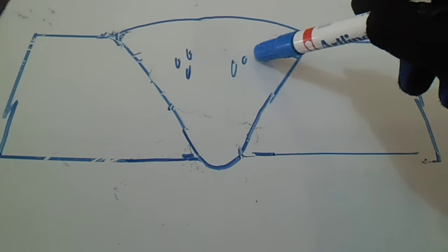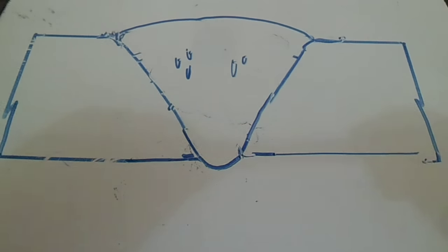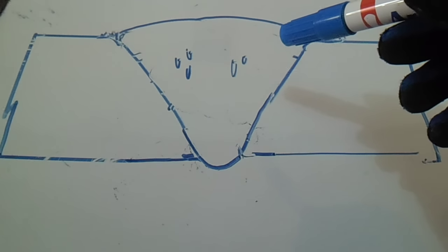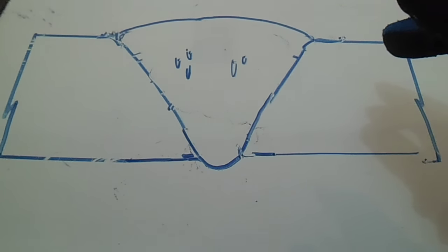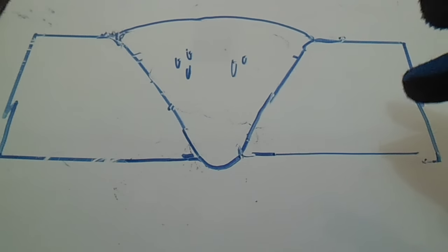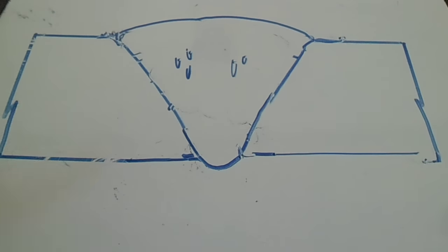So if you see this one, this is porosity. Okay, porosity, because of welding without protection. Okay, the condition of your environment during welding, too much wind, windy, and you have no protection, or the welding rod is not dried, and also incorrect weaving, or incorrect flow of gas, so that the porosity comes out from the weldment. Okay, this is also rejected. Okay, next.